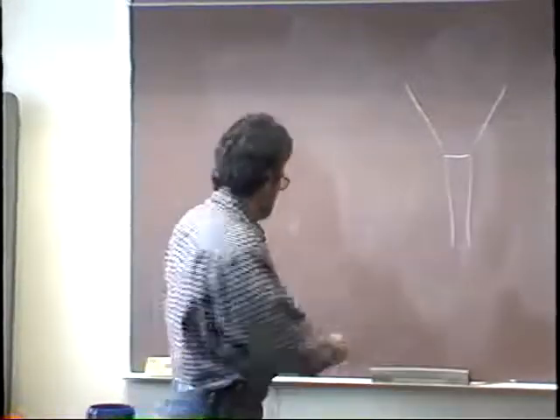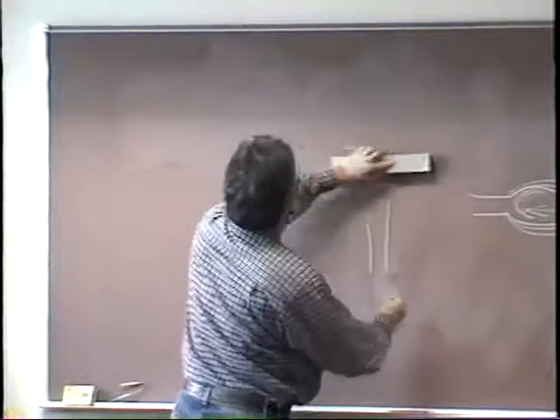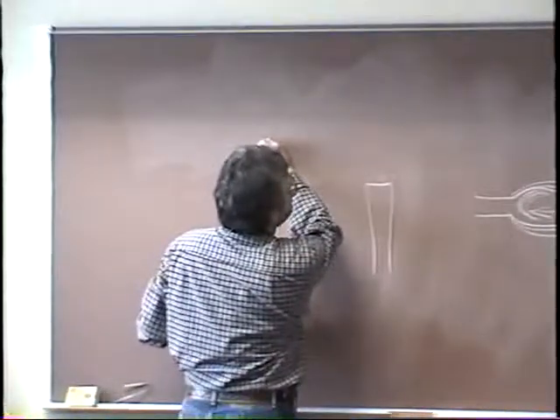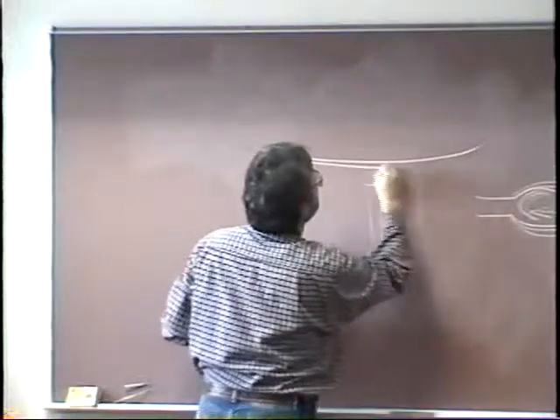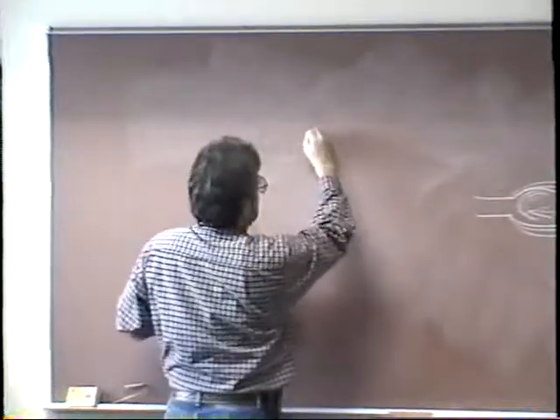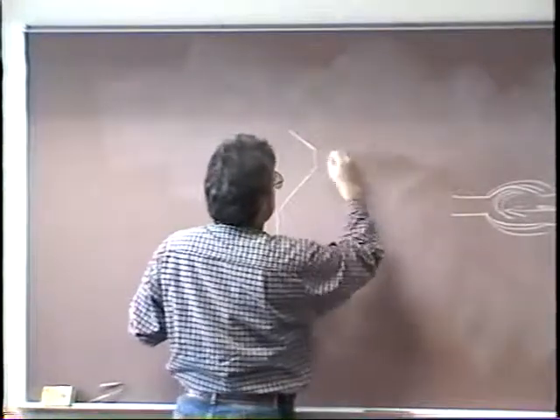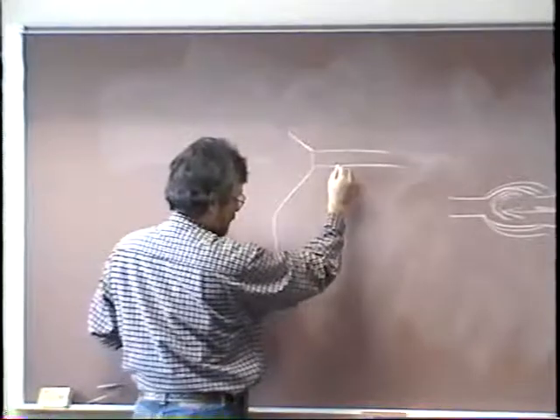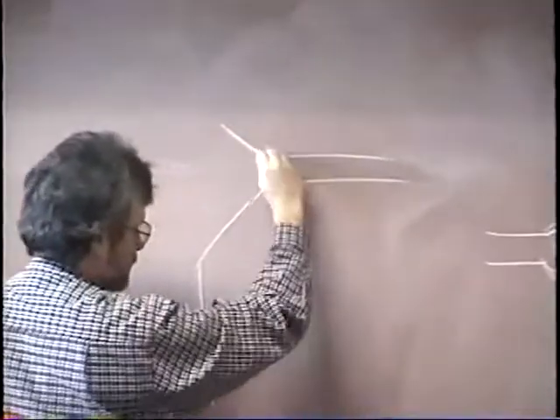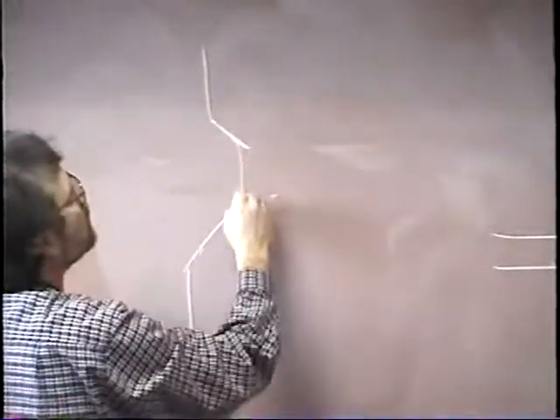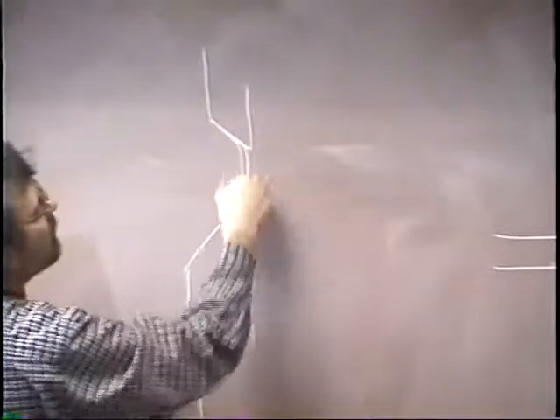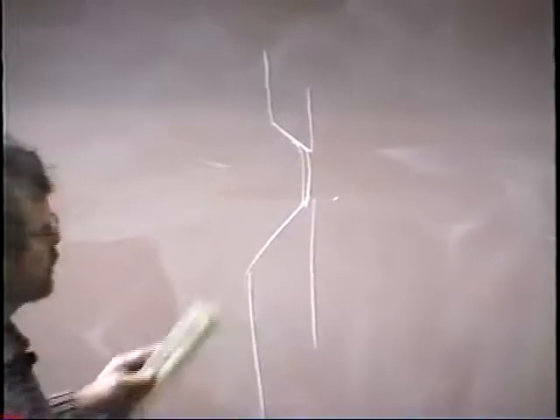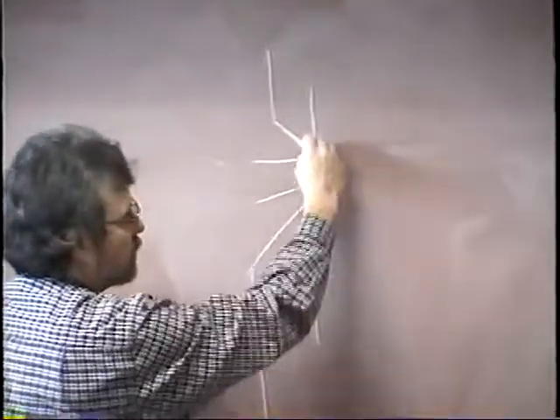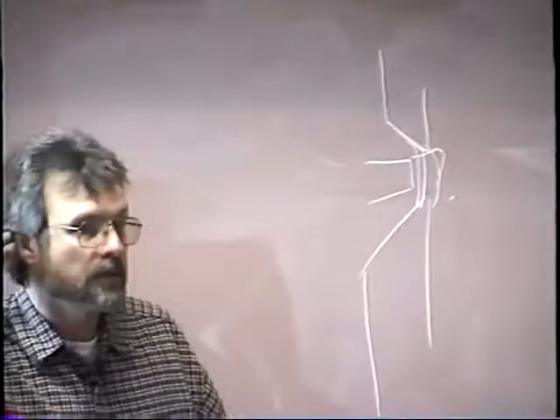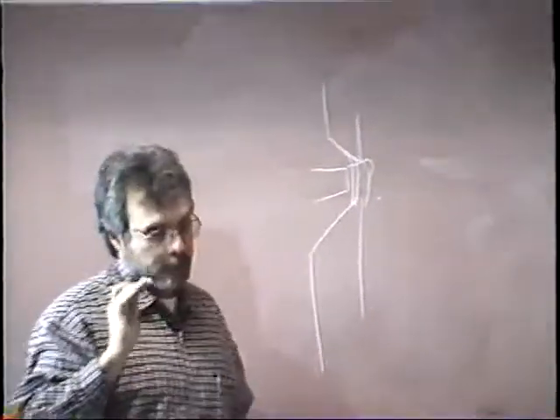And if you long arc it, instead of penetrating inside of this thing, like we want to do, what you're going to do is you're going to bridge it. You're going to bridge it and get lack of penetration. If you long arc it, it's going to bridge. So you want to keep that shoved in there nice and tight so that you're getting through to the other side. And again, the key is still listening for that sound of penetration. If you can hear that, you're getting through.